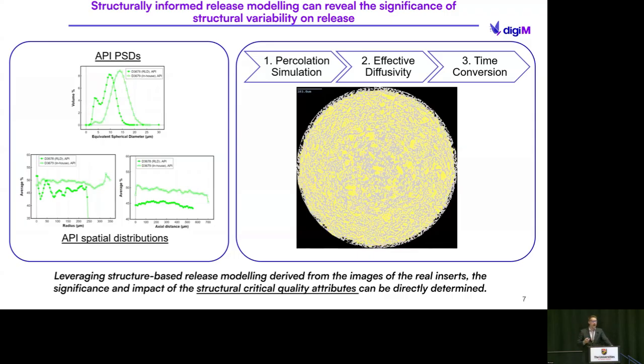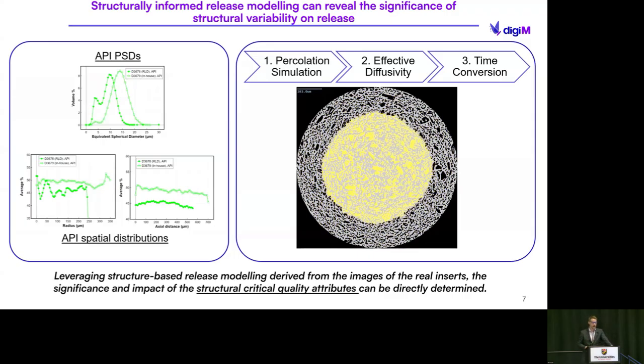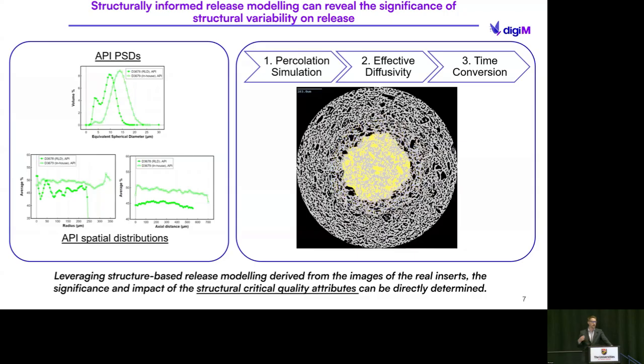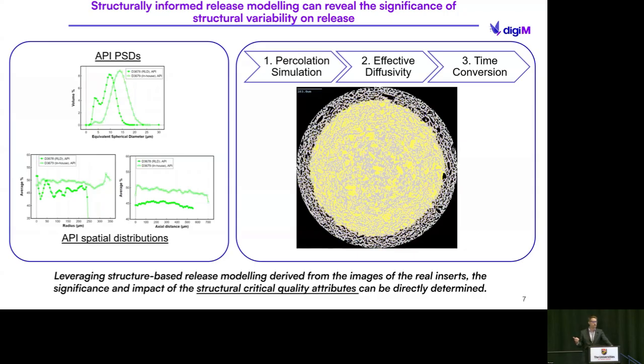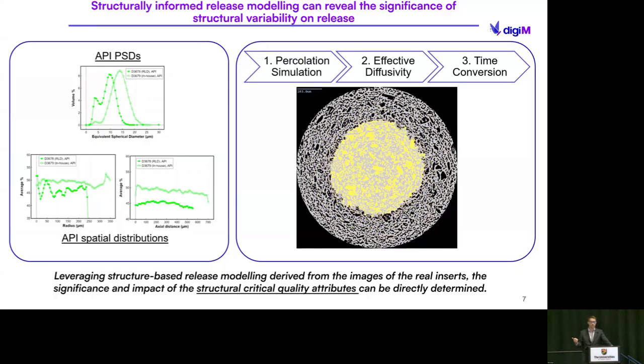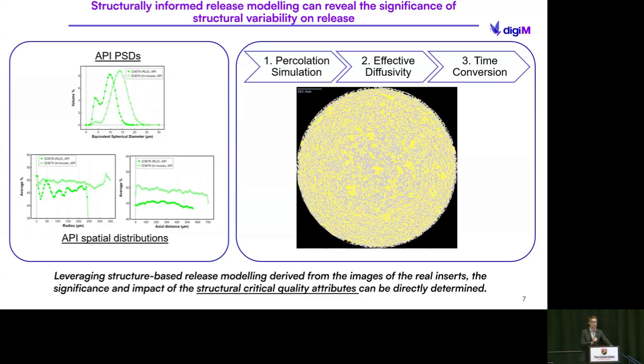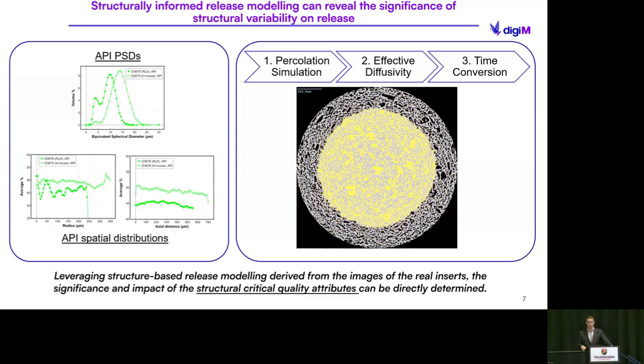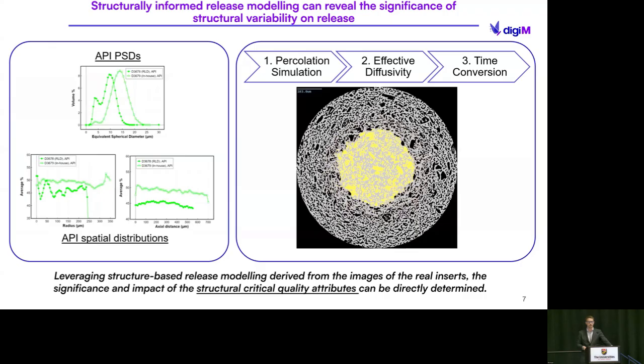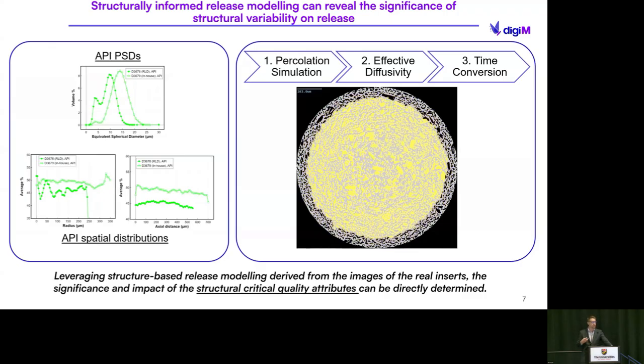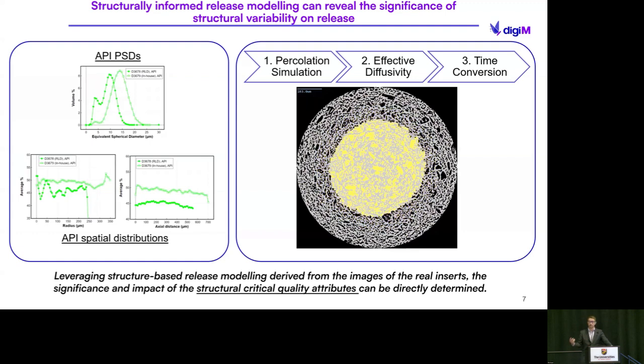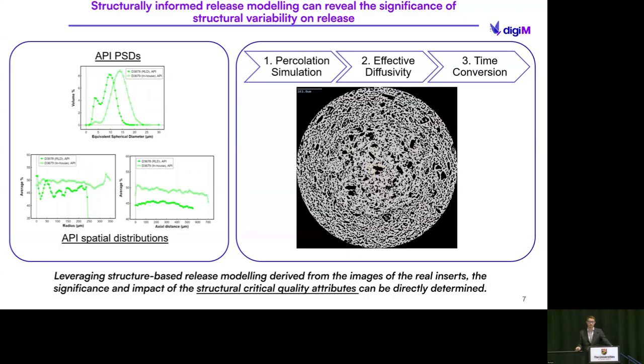And on the right shows how we simulate drug release. And there's a three-step process. I'm not going to go over all the details of it, but we first find out all of the different diffusion pathways through a percolation simulation. We then simulate the changing diffusion coefficient based off of that geometry. And then using an appropriate physical model, we do a time conversion. In this case, the physical release mechanism that we figured was most likely the case here, given the polymer properties and the drug properties, was monolithic diffusion.